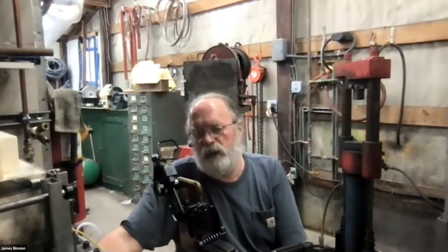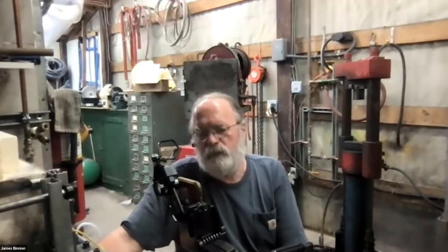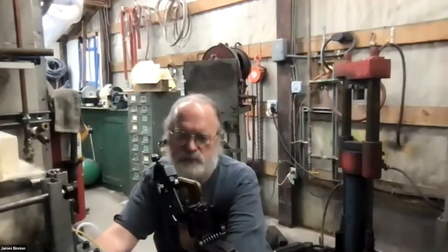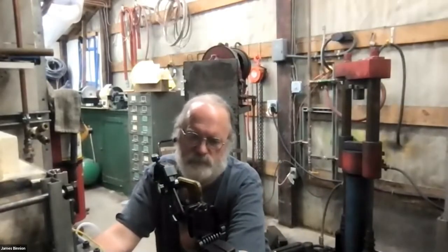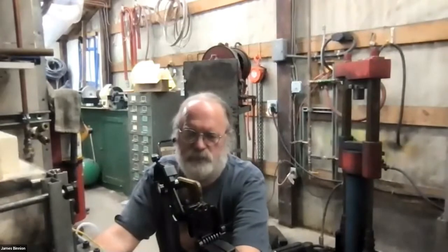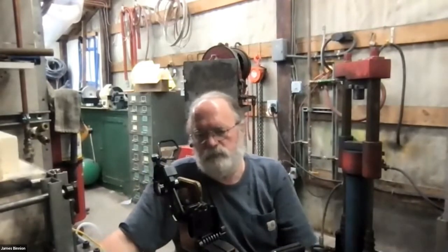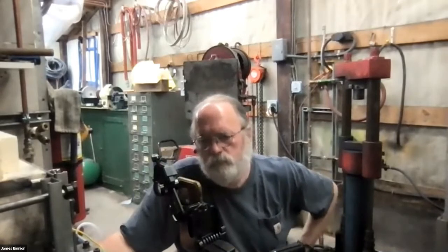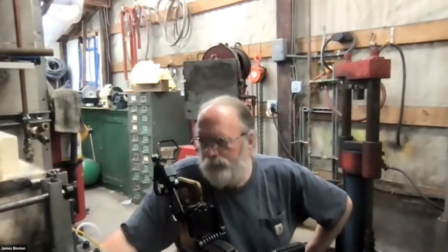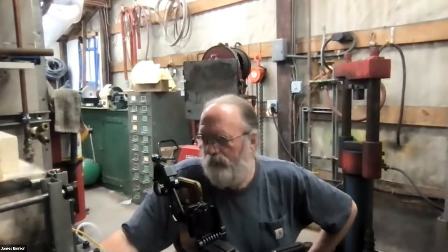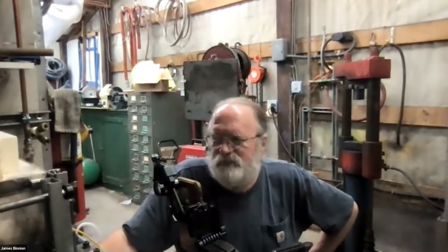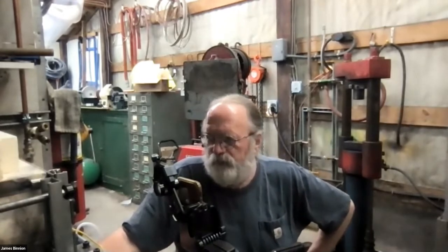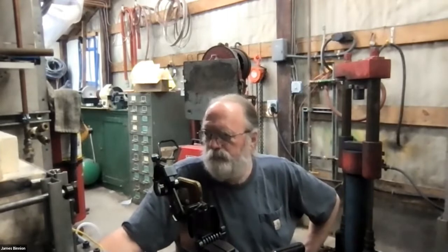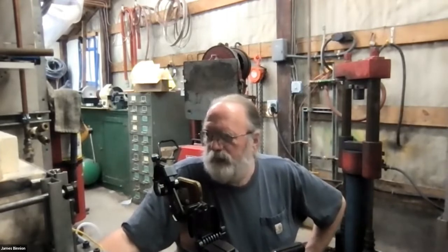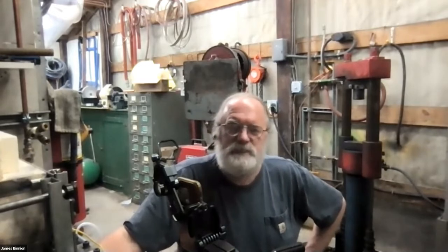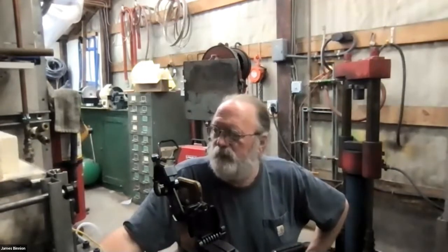For reference, we're sitting right now and have been for the past probably 10 minutes at 1518 degrees, 1520, which is kind of just right about in the sweet spot for this material. And so then how long do you let it soak at that temperature for? Basically 10, 15 minutes is enough if everything is right. And by everything is right, I mean you've got a good compression on the stack, and you haven't had any other issues.